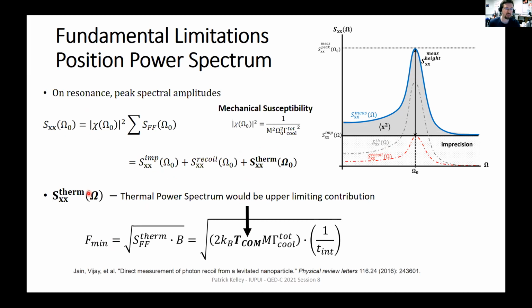And if we're looking at that, what is the minimum force that we can detect given this thermal spectral distribution? It's going to be dictated by the center of mass temperature, meaning the way it oscillates around. This is distinctively different from the internal temperature, which is basically if it's becoming really hot, like red hot. So this is the motional temperature of it. And so to be able to measure definitively a very small force, you have to lower your center of mass temperature.